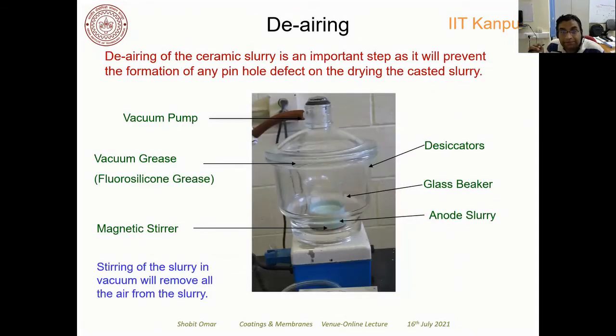Okay, so what is the process of making ceramic slurry? So here I have given it. The first step is de-airing of the slurry. First you ball mill your slurry, and then you take the slurry out, and that slurry may have some entrapped air, right? You do not want that entrapped air to be present when you pour the slurry inside the tape caster. So you have to de-air the slurry, and this is the experimental setup to de-air the slurry.